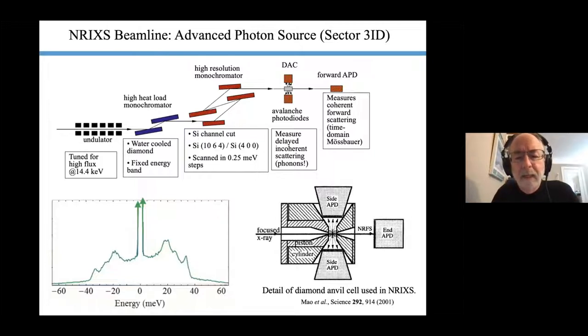This was done at a higher temperature. So I do recognize the features of the basic phonons of iron. Here's the longitudinal modes, the high and low transverse acoustic modes. And there's some multi-phonon scattering up here, which comes about when we create two phonons and we get outside the range of the phonons. Anyway, we have to correct for things like that at high temperatures, and we do.